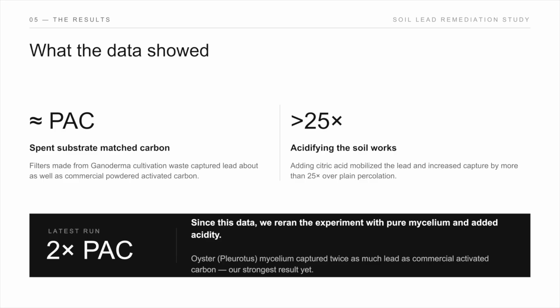And then our last run of this actually showed that the biofilters perform twice as good as the powdered activated carbon. So the first ones we did with just a spent mushroom substrate were basically neck and neck. But the most recent ones we did prioritized using pure mycelium rather than the spent mushroom substrate. The Pleurotus species was twice as good as powdered activated carbon for this very short experiment. So, hugely, very good finding. We're going to continue to do this research, and you'll see in a couple slides how we're looking to do this at a site level, at a demonstration level rather than just a laboratory.